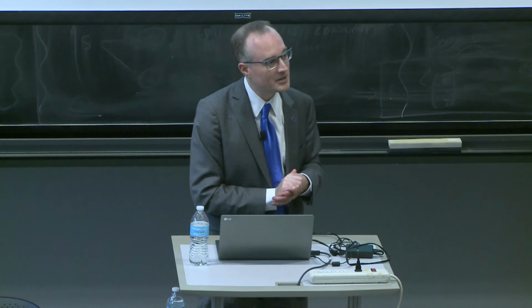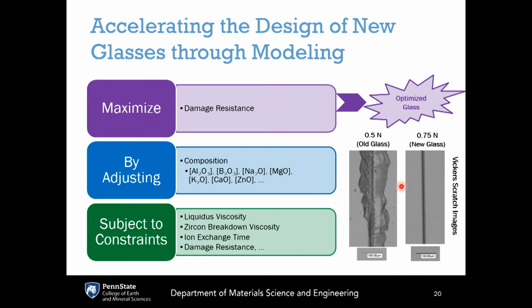And when we have these models set up, if we have an accurate model for every one of these properties that we care about, all of the product-related properties, all of the process-related properties, each one of them as a function of composition, then the design of a new glass becomes really a mathematical optimization exercise where you've got some property that is the most important property that you need to maximize or minimize, and another set of properties that need to be met in order to ensure manufacturability. And if you do that, then you can get the next generation product. And that's exactly what this is.